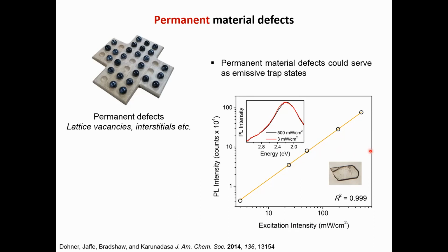But in our cases, until we burn the material, we have never seen any deviation from linearity. It's always a perfectly linear relationship. So with this, we can make two conclusions. Either this material has a ridiculously large number of defects such that we never saturated, which I find hard to believe in these beautiful single crystals, but it's possible. Or alternatively, this is not the correct model. We have something else going on.